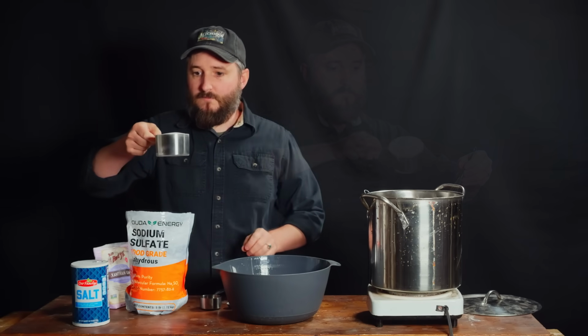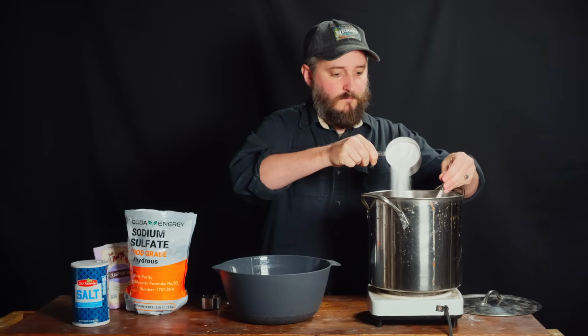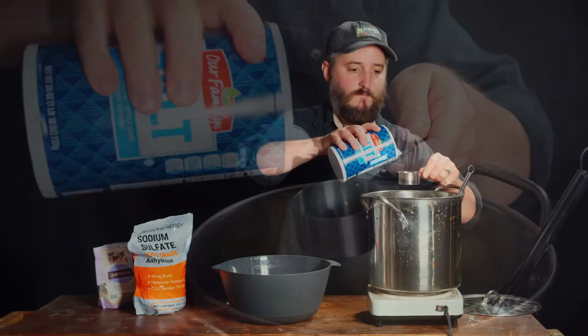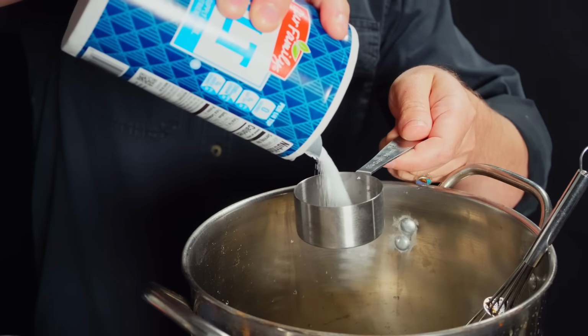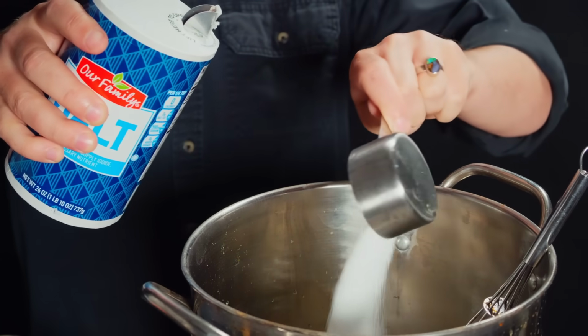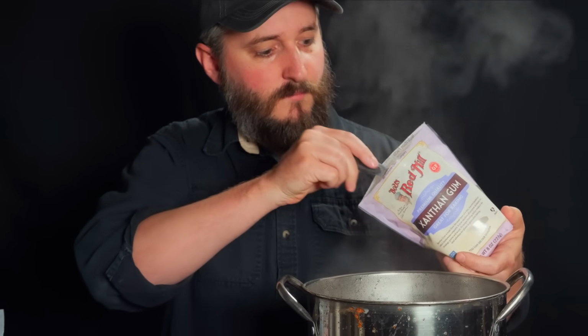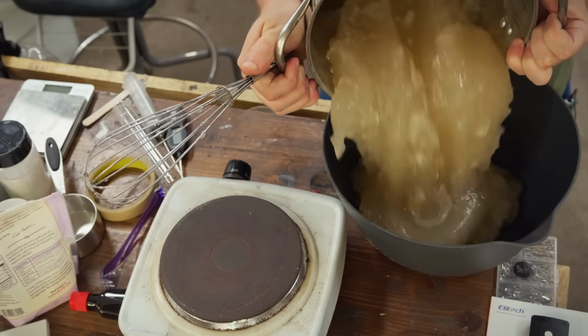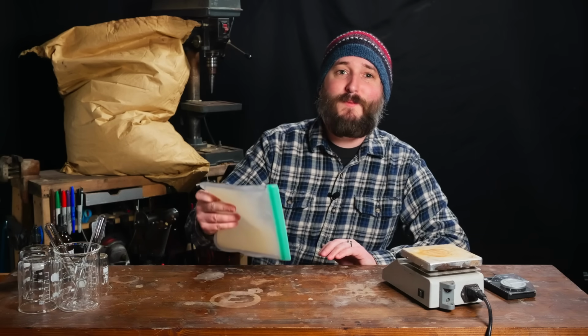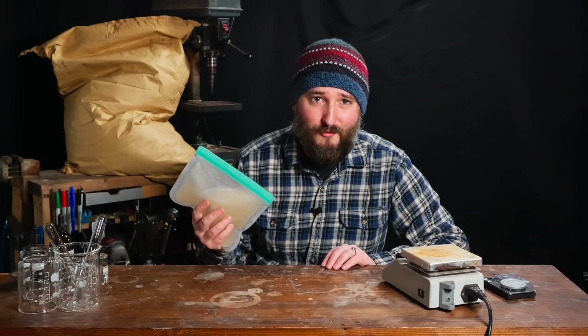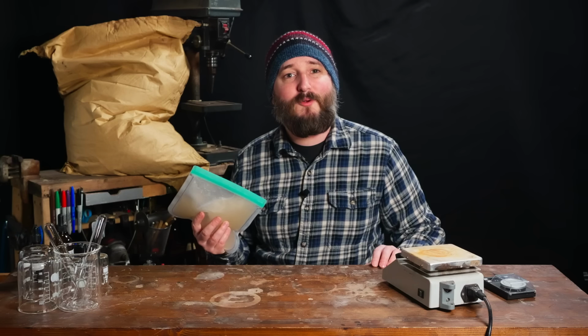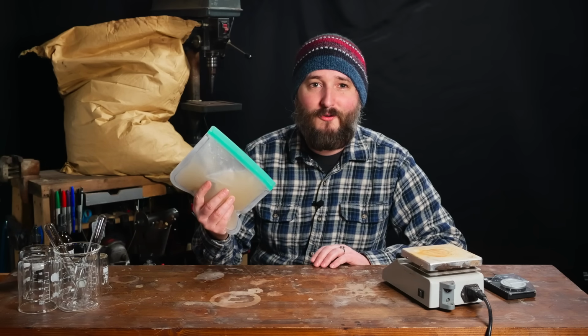To recap the earlier project, we made these by adding sodium sulfate to hot water until no more can dissolve. Add in some table salt to lower the melting temp, and a thickener like xanthan gum to make a stable gel. These bags of the finished PCM are amazingly useful, freezing right around room temperature and staying comfortably cold for hours on end.